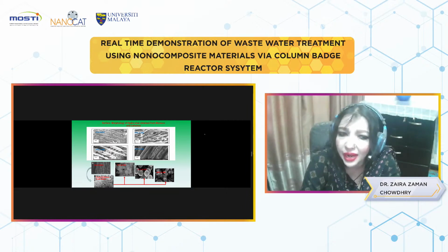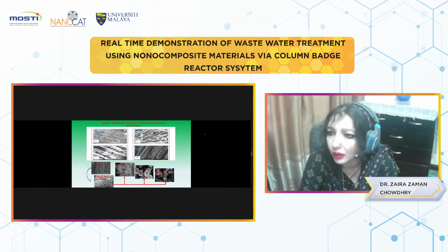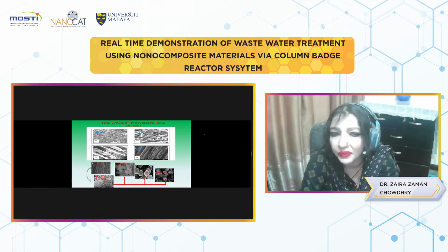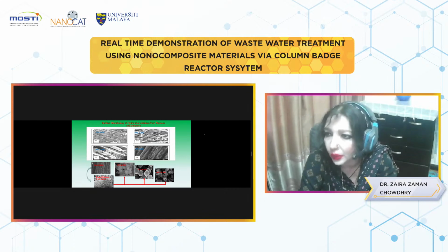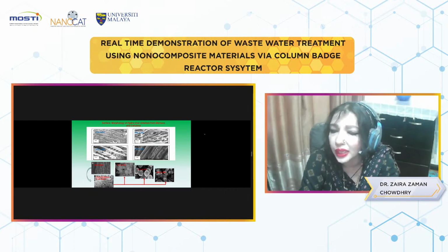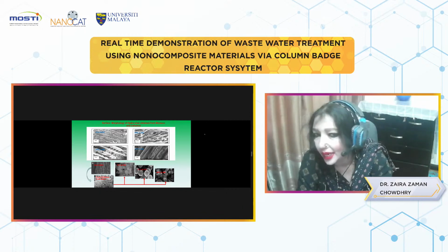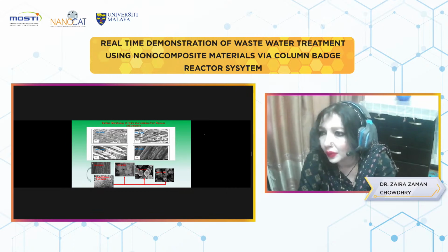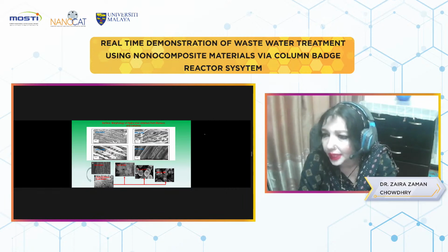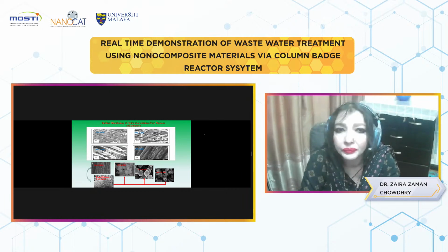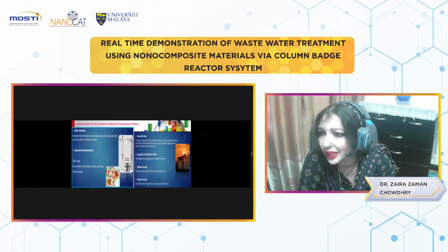In second step, what we have done, from rotten sawdust, we have extracted the cellulose by hydrolysis process. Those cellulose we did the hydrothermal carbonization at 200, 230 and 260. So we got a new types of carbon, which is globular shape, cluster shape, carbon globules. These types of carbon are not that much good for adsorption, but for electrode material, it has been found good. It has been found to work better. So these are some use of activated carbon.